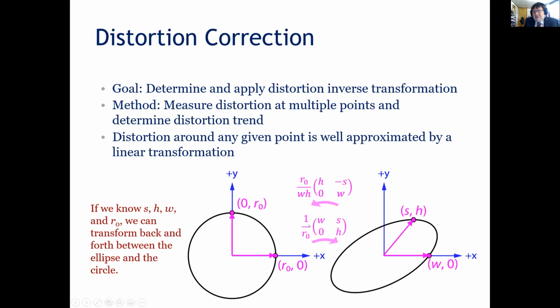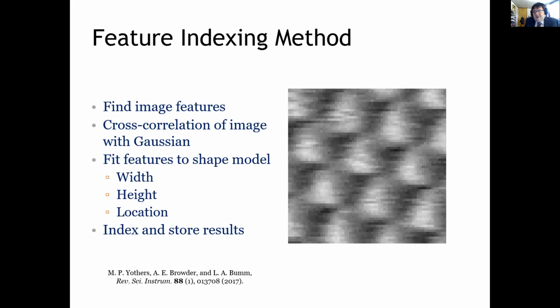So using some simple linear algebra, this is what a single point in a distorted image would look like. It has some shear, it has some change in height, and it has some change in width. If we could determine these parameters, we can transform back and forth between the distorted and undistorted images. So we get the computer to determine the feature locations for us. So that could be carbon atoms in a graphite lattice, or terminal groups of alkane thiols, or whatever features you're looking at in your scanning tunneling microscope image.